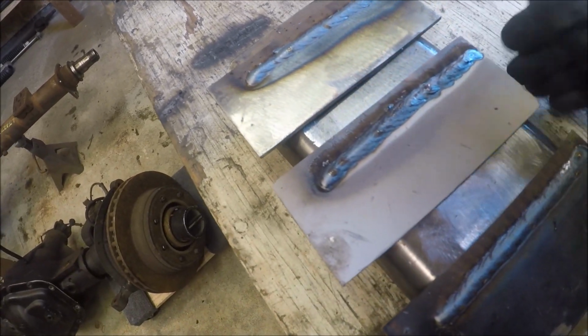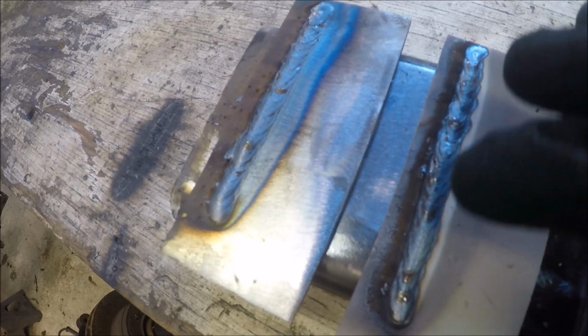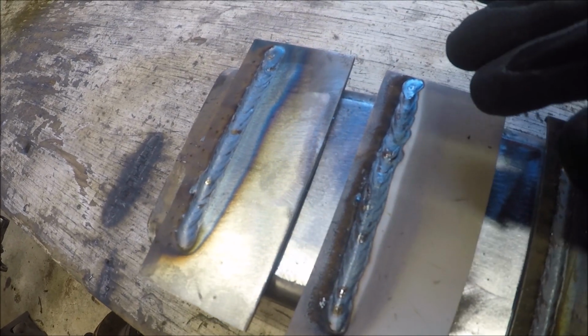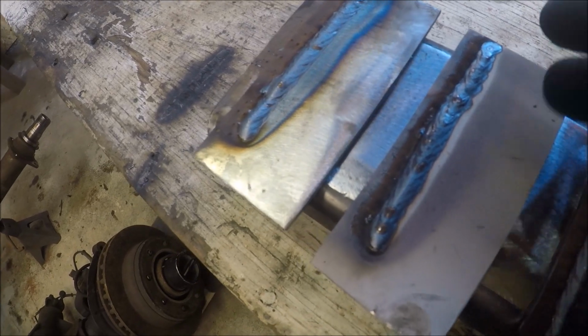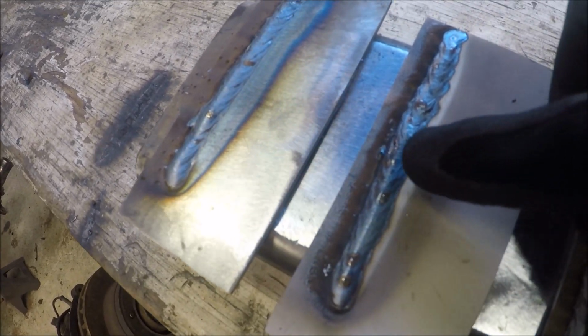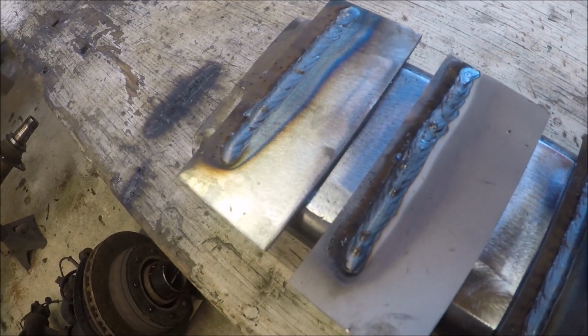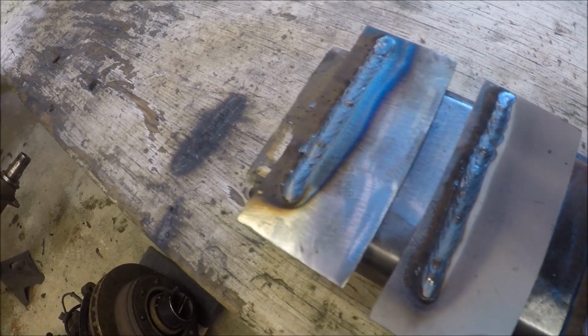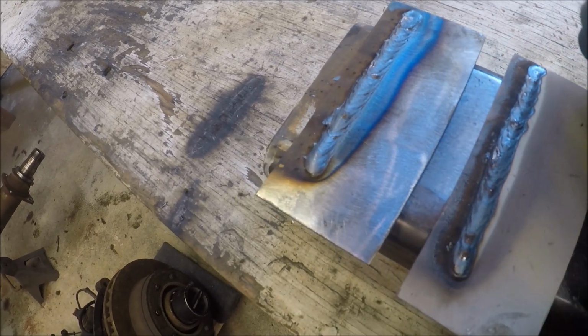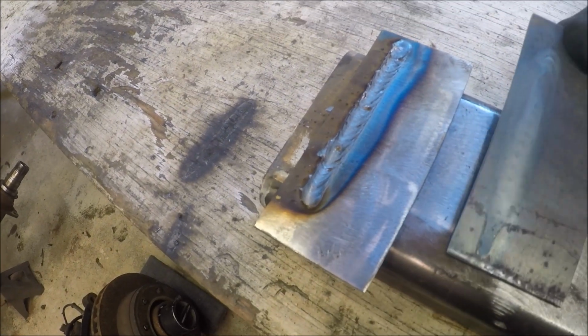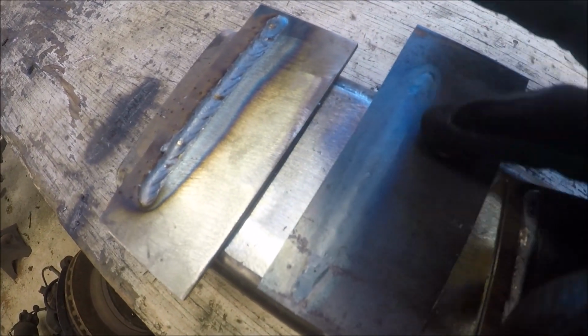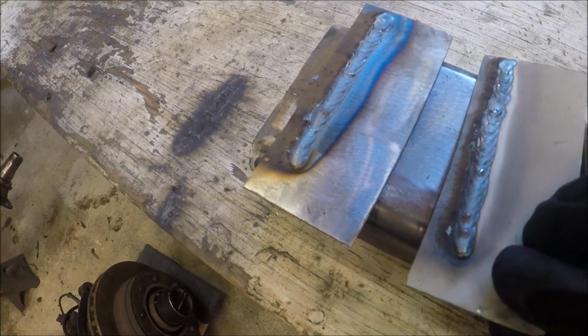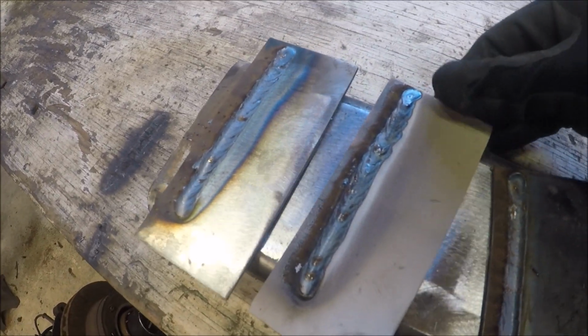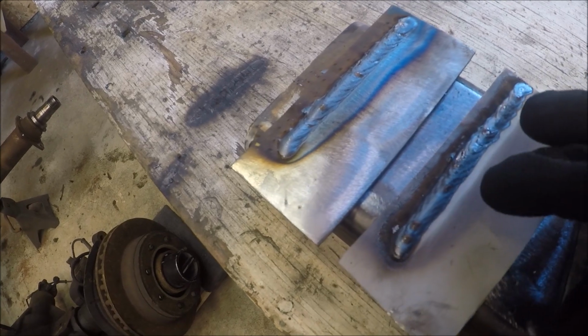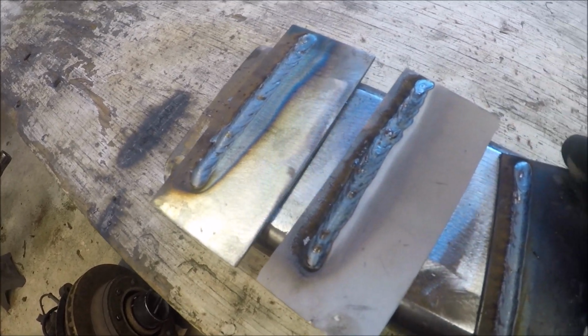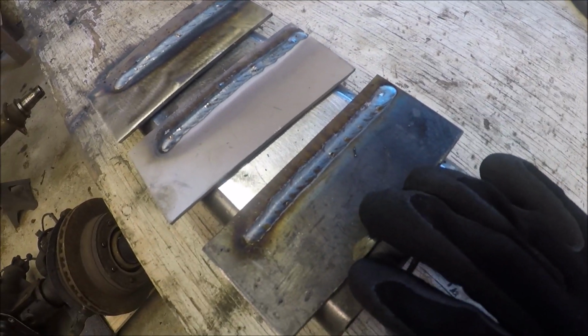Now, here is the weld-through primer. Now, it's a little harder to tell because obviously the weld melts where you laid down the bead, but a couple signs maybe of a little bit of porosity. But as I was welding, the puddle looked the same as this, and I was actually really surprised. And when we talk about transfer of heat, again, you can clearly see that this is penetrating very well. So I'm pretty happy with that. There was a little bit more splatter with this, and maybe we can talk about why that happened after we conduct a little bit more of the experiment.